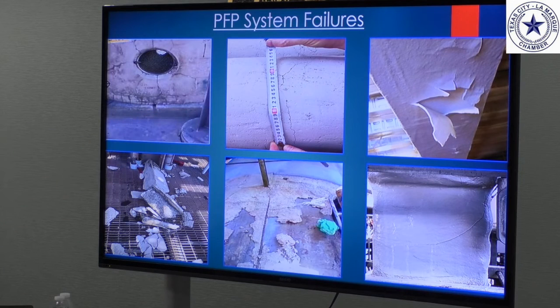This lightweight cementitious product was installed on a process pipe operating above that 185 temperature threshold. You start seeing the dehydration, the cracks, moisture finds the path of least resistance. You now will get corrosion under fireproofing at some point, and it will lead to the same type of scenario. Disbondment and detachment from the steel. So again, dropped objects, unprotected steel.